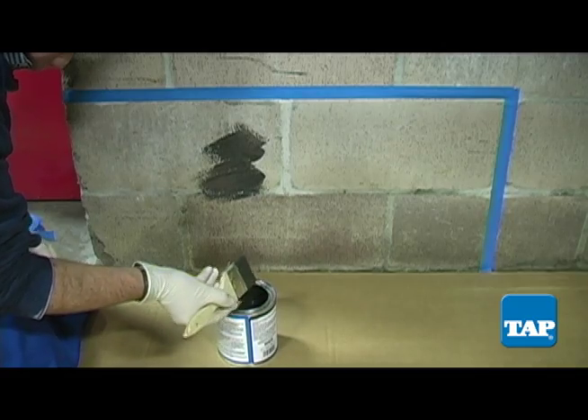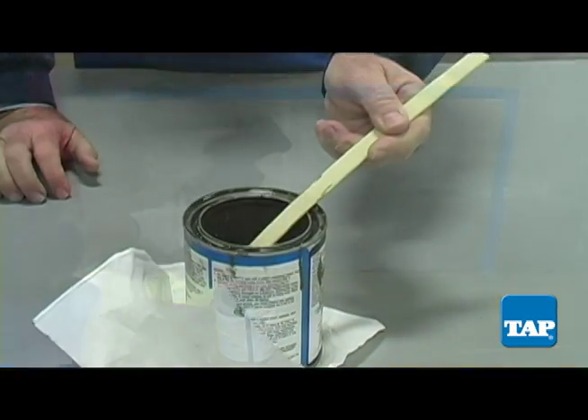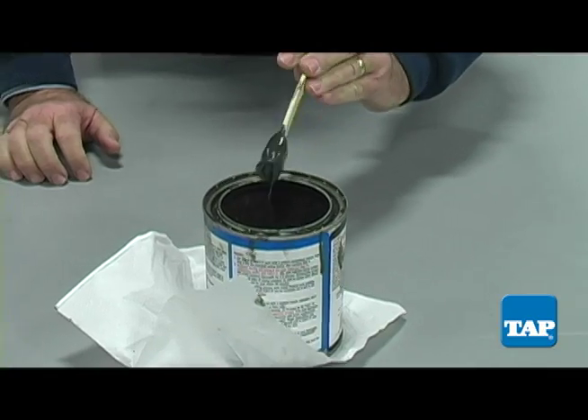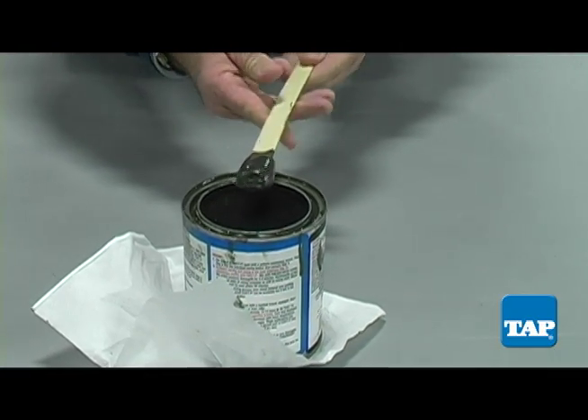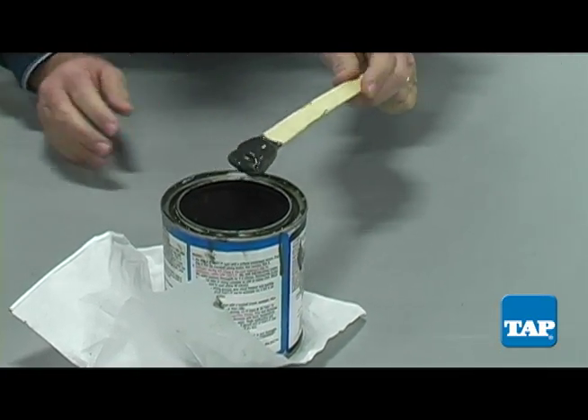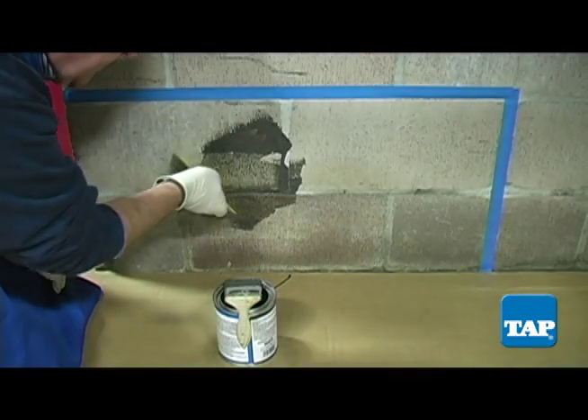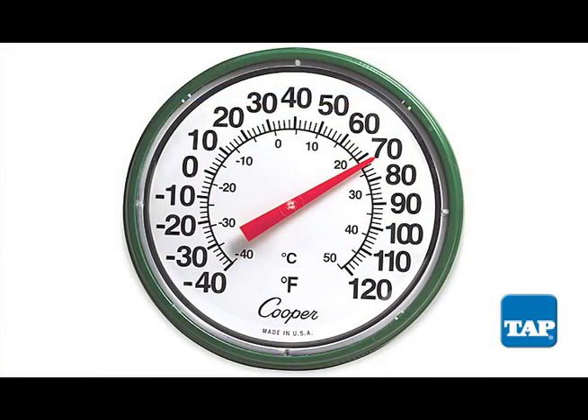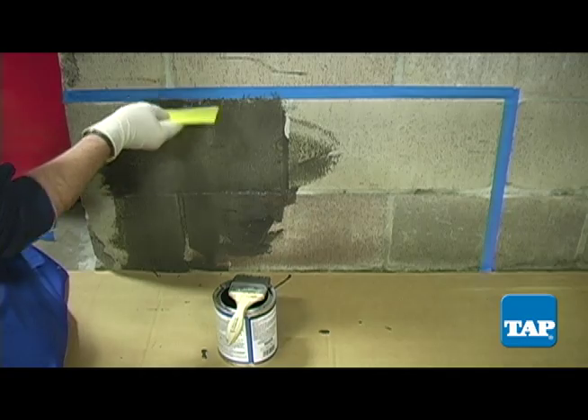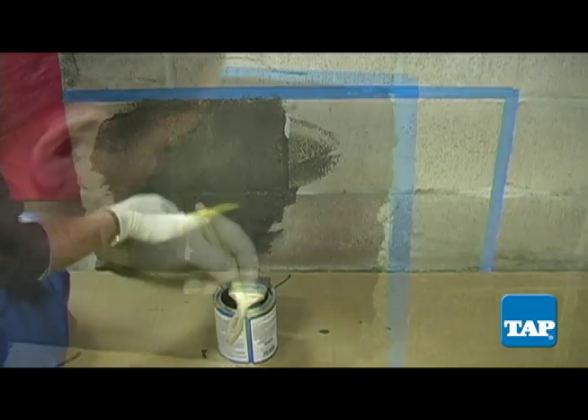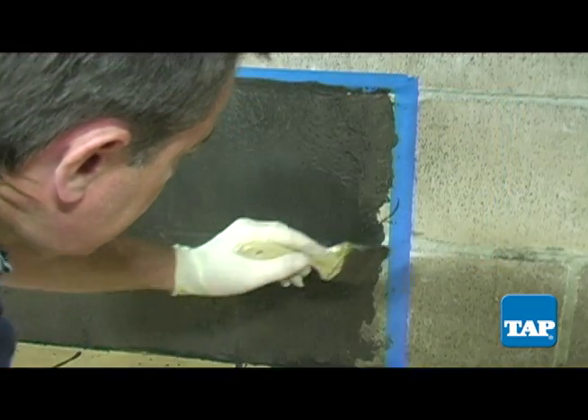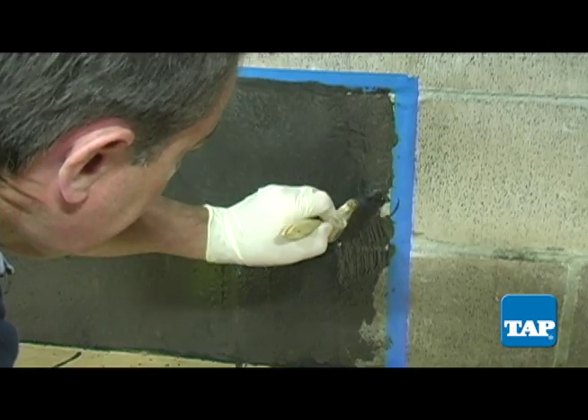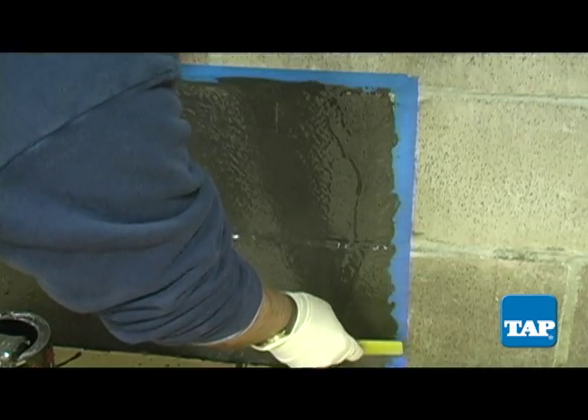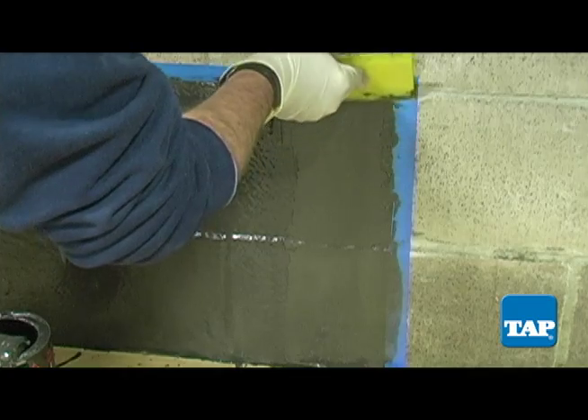A characteristic of Coat-It is that after a time it thickens before it hardens. Thickened material left behind in the container can then be used for areas that need special attention. At 70 degrees, Coat-It will be fully cured in 10 to 12 hours. At lower temperatures, cure time can be much longer, and at higher temperatures, it will be shorter. A second coat of Coat-It can be added after the first coat gels, if desired.